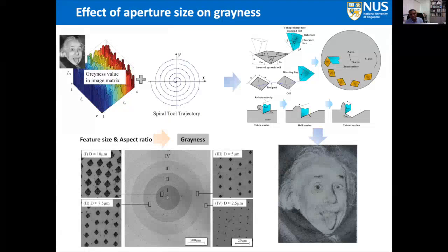All this complete image is produced by means of chiseling, where you make micro dots on the surface, similar to what is shown on the left-hand side. By characterizing the feature size and the aspect ratio, we are able to determine, depending on the grayscale value, what should be the aperture size and the depth, and we are able to produce an image like this. You can easily see how good the quality of the image is, especially the hair. Even the hair is all clearly visible in this particular image. So we are able to produce very interesting features out of this technique.